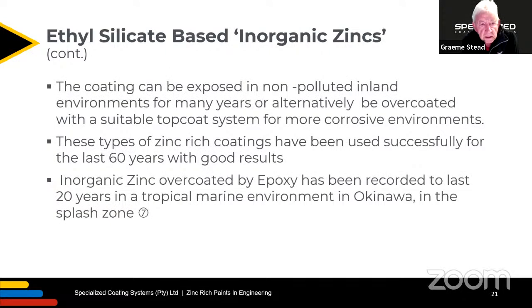The coating can be exposed in non-polluted inland environments for many years, or alternatively be overcoated with a suitable top coat system for more corrosive environments. These types of zinc-rich coatings have been used successfully for the last 60 years with good results. And inorganic zinc overcoated by epoxy has been recorded to last 20 years in a tropical marine environment in the splash zone.